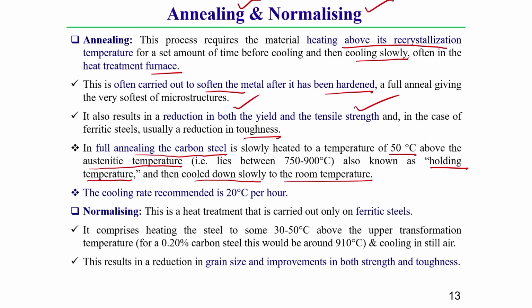Here one thing you should keep in mind: in the annealing operation the cooling rate is very slow. The cooling rate is around 20 degrees centigrade per hour, that means per hour only 20 degrees centigrade of temperature will be reduced. This you should keep in mind.